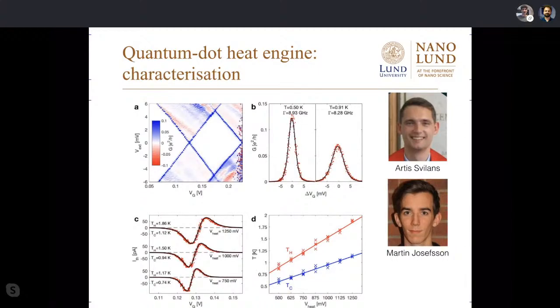And again, the red dots are measurements. The black line is now a fit to the measurement using the gammas that we have determined already as an input parameter, but having the temperature on the cold side and the hot side as fit parameters. So from this fit, we get also a delta T. And on the bottom right panel here, you have the extracted temperatures on the hot side and the cold side based on these fits that you see here. So that gives us a delta T.